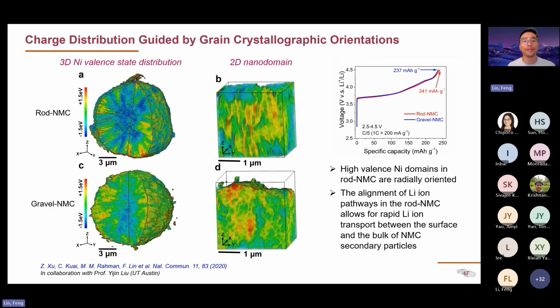One example of different behavior in this chemistry is the charge distribution. The way we did this was to charge the two different types of materials to the same state of charge, and then map the nickel oxidation state distribution inside individual particles. Then you can figure out which part of the particle gets oxidized and which part hasn't. It turns out that with the rod NMC, the charge domains are radially aligned, which is very similar to the grain microstructure that you're building. So this is experimental data demonstrating that with the same chemical composition, you can get different state-of-charge distributions inside the individual particle.